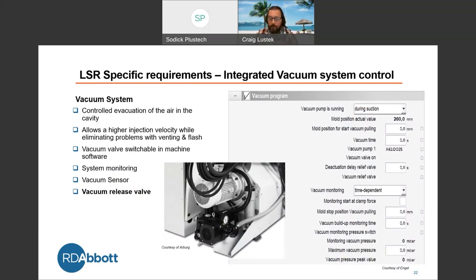The vacuum valve switchable in machine software is available. Always talk to your machine manufacturer about that. You have the system monitoring as well as the vacuum pump and the setup. Always get your vacuum release valve. That's very important. That way, if you're using vacuum seals in the mold, when you open, you don't still have vacuum set on your mold. Otherwise, as you open, you pop the mold and you could damage your part. So always make sure you have that vacuum release valve set up in the system to depressurize it to allow that mold to open properly, where you don't damage any parts.